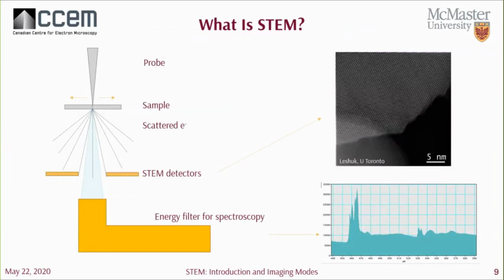Nonetheless, STEM is quite useful, and as you probably have seen in lots of literature, it's a quite common technique that is used to characterize materials. We can operate the TEM in STEM mode, where rather than using a parallel beam to illuminate our sample, we converge the beam to a probe and raster across your sample in the X and Y direction. We use electromagnetic lenses to help collimate or focus and demagnify the electron beam onto our sample. It's very similar in nature to an SEM, but one major difference is that we're collecting electrons that have been transmitted through your sample